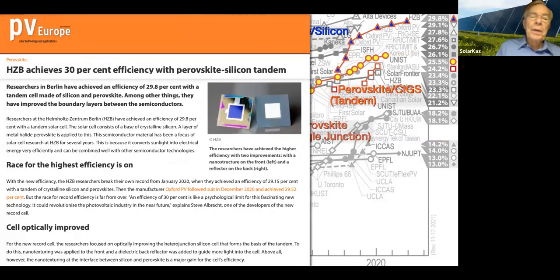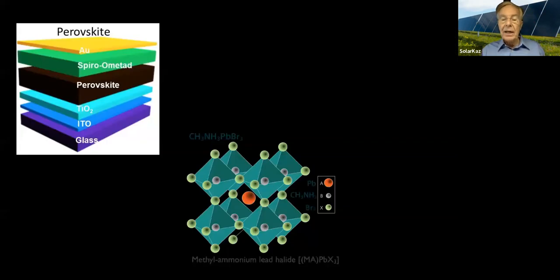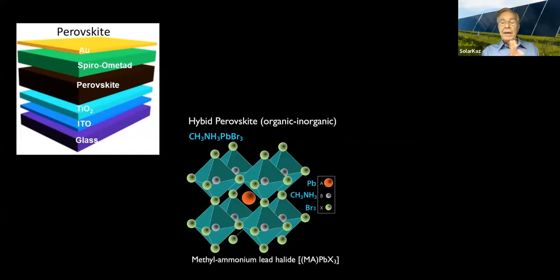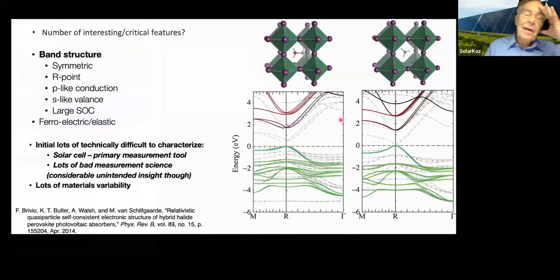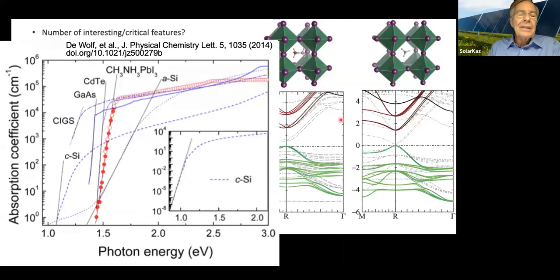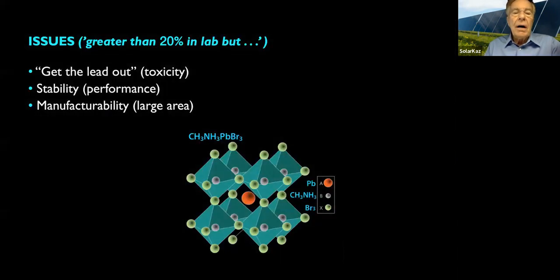So here is the 30% efficiency on the silicon tandem, just recently announced within the last 6 months or so on this. And this material looks like this. It's a hybrid organic, inorganic thing. The organics now with lead, okay, tied up with some other materials, and the organic stuff surrounds this whole thing. And of course, there are some concerns with this. It's a complex material, but has all the stuff you want. It's a direct band gap semiconductor, which means you can make very thin layers out of it to absorb the sun's energy. It has absorption coefficients that are the same as the best that we have for solar cells. It has some problems.